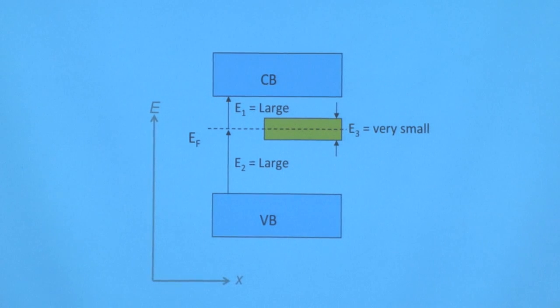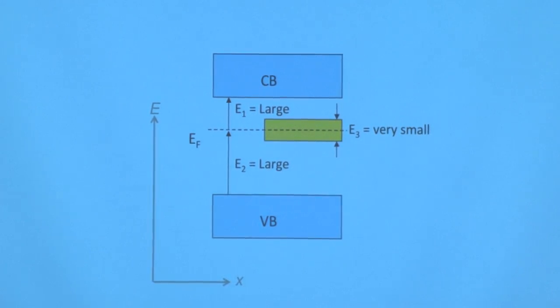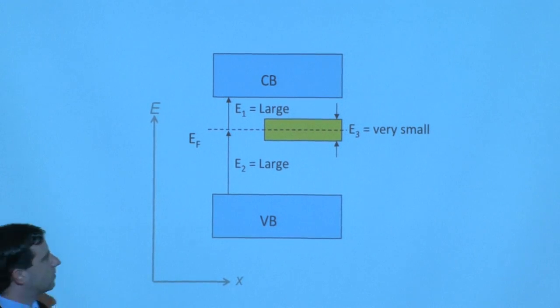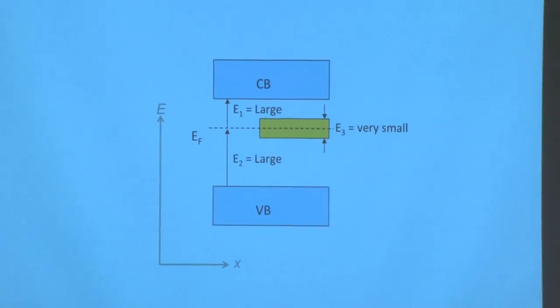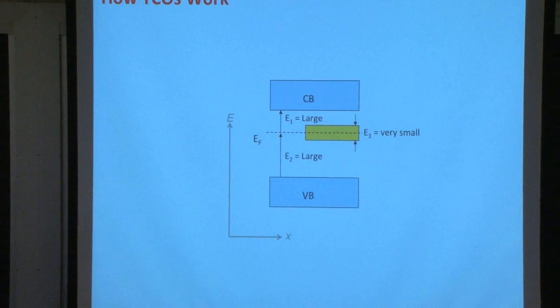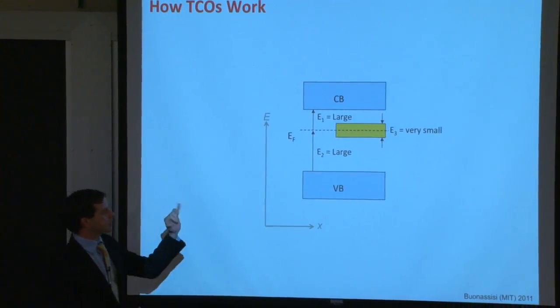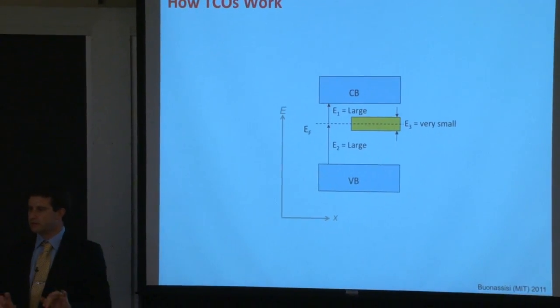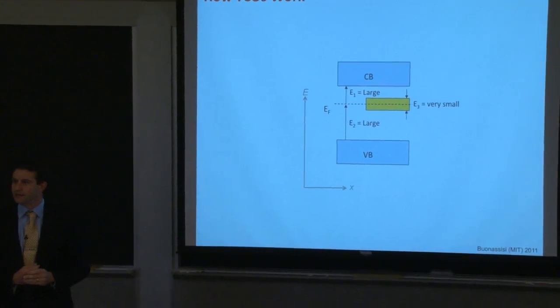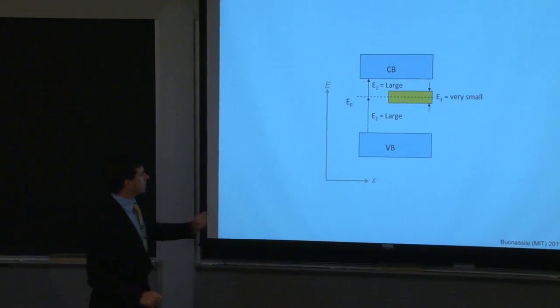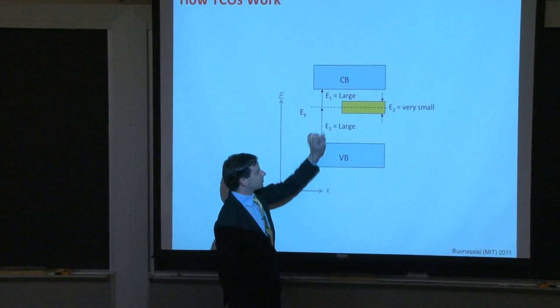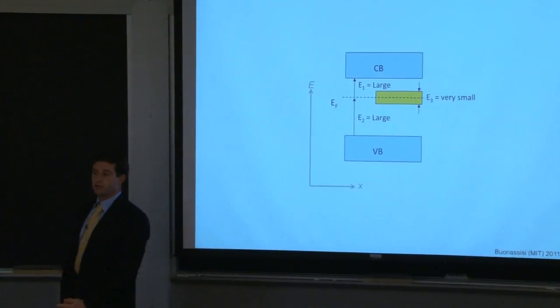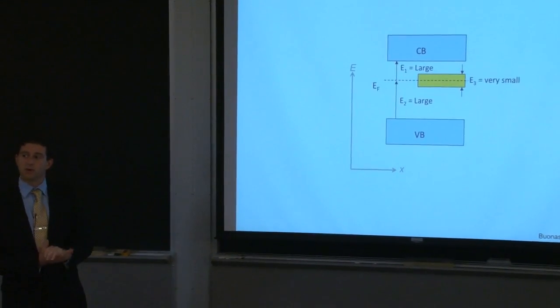Any questions so far? Because this is kind of important before we launch into, yeah? So how big are those? Is that E1 and E2? Yeah, so this E3 right here is around 0.4 eV for a typical TCO. And E1 and E2, the sum of both of them could be on the order of 3 to 4 eV, maybe higher. Well, actually, no, sorry. Just one of these transitions right here could be on the order of 3 eV. So the entire band gap could be quite large.